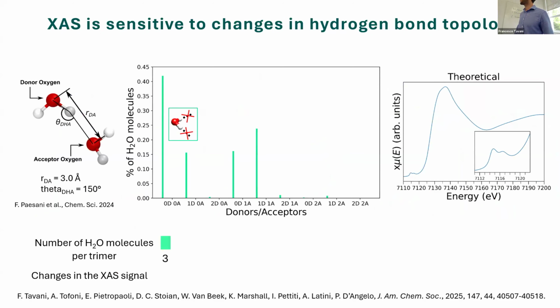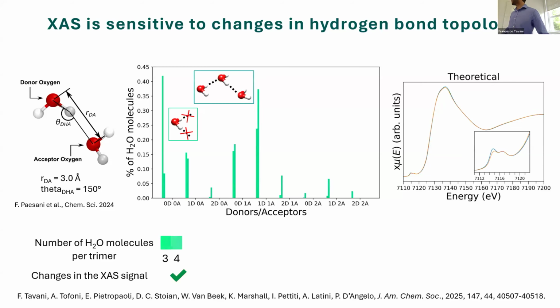So if we look at the changes in hydrogen bond topology as a function of water loading, we can correlate them to the spectral XAS fingerprints. This was a very rough analysis of the hydrogen bond topology based on the MD simulations. When you have a number of water molecules per trimeric unit equal to 3, we defined different possible donor-acceptor arrangements for the water molecules. You have, for example, a certain amount of water molecules that do not donate and do not accept, 0D and 0A hydrogen bond, which is defined as I'm showing here. Some water molecules donate one hydrogen bond and do not accept any, and some donate one hydrogen bond and accept one.